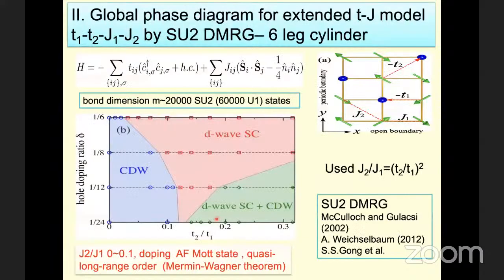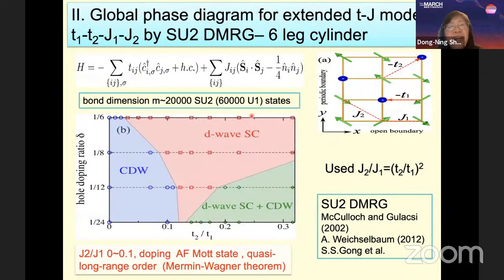You're welcome. So we have done a very extensive study of the t-J model. In our t-J model, we allow nearest neighbor and second nearest neighbor hopping, and antiferromagnetic coupling. So the second nearest neighbor hopping is what causes frustration on this square lattice.